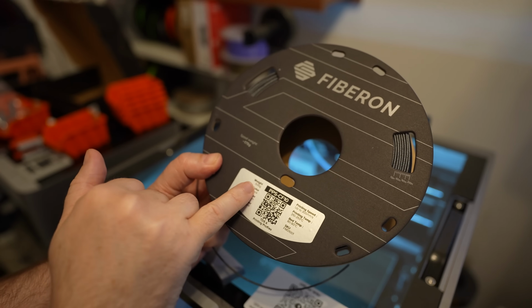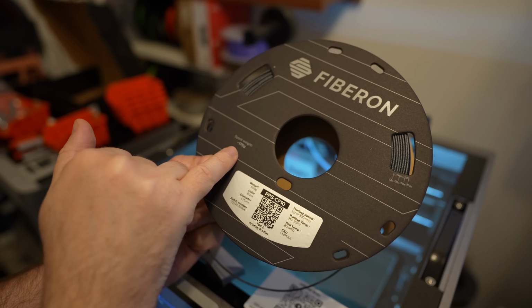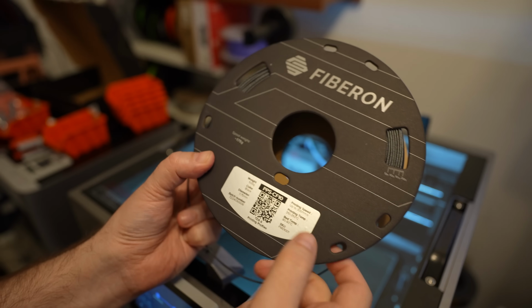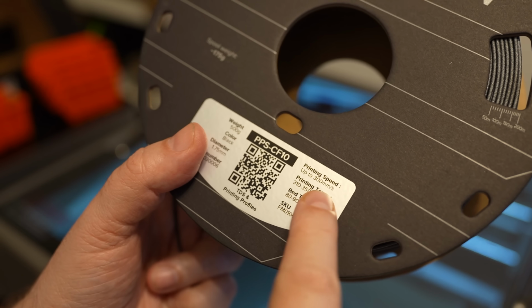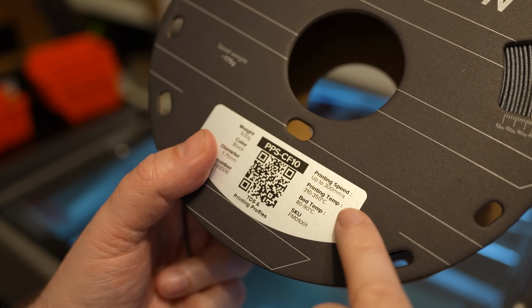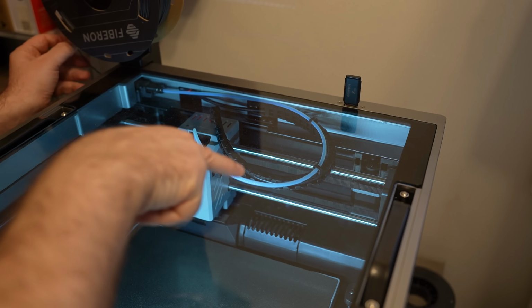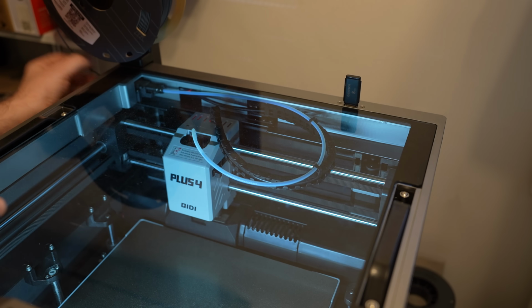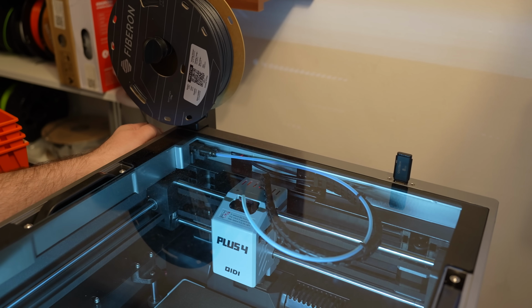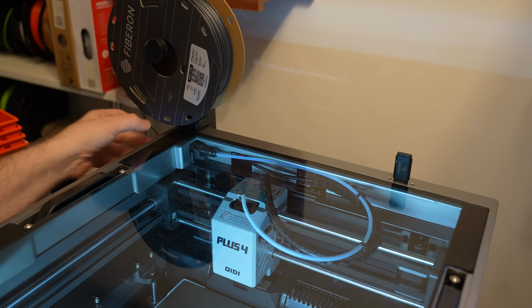We have only half a kilogram of filament and the weight of the spool is 175 grams. And this printing speed of 300 mm per second is really suspicious. I hope it will not break inside the Teflon tube. I can feel that it grabbed the filament. I'm inserting it at 300 degrees Celsius.